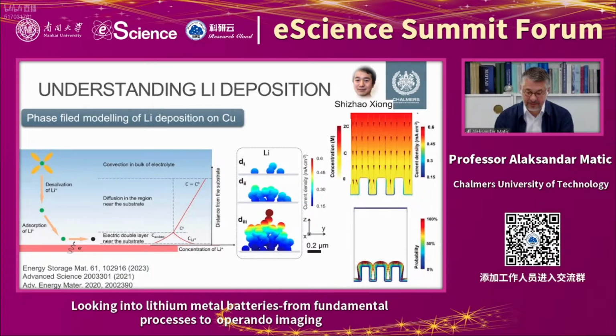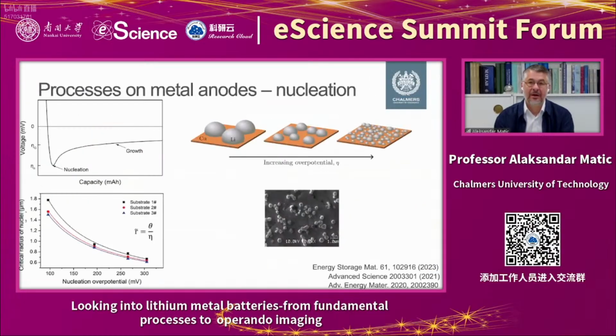And what came out of this work was that the first thing, for this initial nucleation step, which is very important for the final morphology, is that the radius, the size of the objects that are formed initially when you start deposition, is very closely related to the nucleation overpotential, so the value of this peak in the voltage curve. And we could show that this nucleation overpotential and the critical radius were really always correlated.